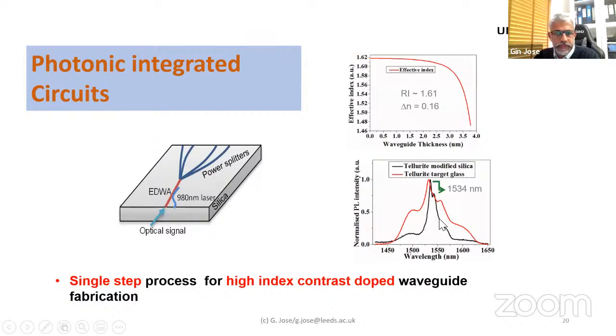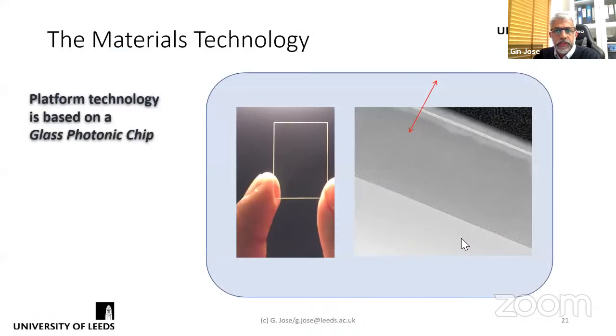Here it shows that the material shows erbium fluorescence when it is introduced into the silica. This is the target glass fluorescence, which is broad, but once it is in silica, it is narrow. So we can use it for different applications.